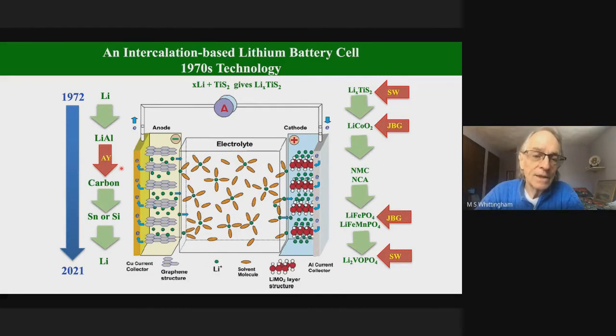A challenge with carbon is that if you have the wrong electrolyte, then the solvent will solvate the lithium, and the solvent will go into the structure as well, eventually destroying it. So this graphitic carbon came on the market around 1990 and is still used today. But it takes up half the volume of the cell and a substantial weight, so it has to go eventually. So we, and others, are looking at replacing it with tin or silicon. Both of these react with 4 lithium ions, but there are issues here, so we'd really like to go back full circle and work on lithium metal again.